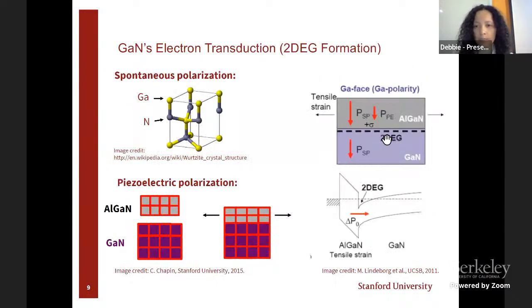So let me go back. We have our heterostructure here, aluminum gallium nitride, and at the interface, this two-dimensional electron gas. This is formed due to two phenomena: spontaneous polarization, so if I look at a gallium nitride unit cell, we have elongation and there's a dipole that's generated, and also piezoelectric polarization. If I grow that slightly doped variant, AlGaN, on top of gallium nitride, due to the lattice mismatch, we have tension in the film, and due to the piezoelectric nature, we're generating a voltage. The combination of these two effects forms this quantum well at the interface, and this is how, again, we have our conductive two-dimensional electron gas, or our 2DEG.